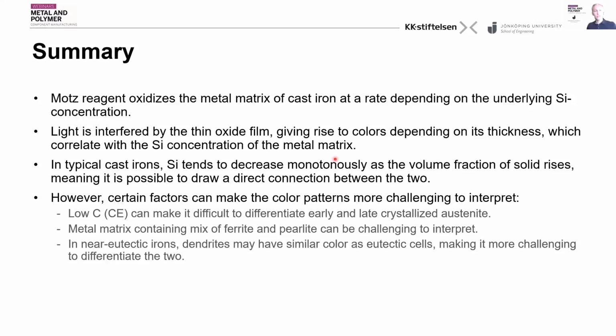At very low carbon equivalents or carbon contents, it can be difficult to differentiate early and late crystallized parts of the austenite because the color can be yellow both early and late in solidification. Moreover, a metal matrix containing a mix of ferrite and pearlite can be challenging to interpret as they etch at different rates. And in near eutectic cast irons, dendrites may have similar color as the eutectic cells, which makes it difficult to distinguish the two.